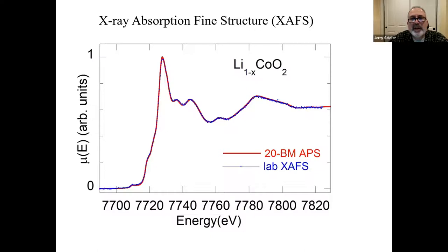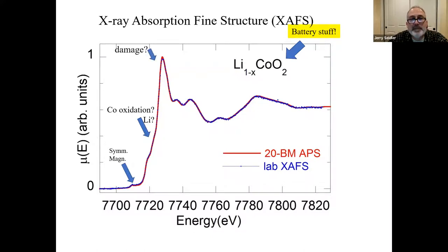Of course, there's a considerable infrastructure for interpreting these spectra, but extremely briefly, and it's a battery material. From the pre-edge features, you can often learn about symmetry and sometimes about magnetism of a material. From the position of the edge, you could learn about oxidation state, in this case, possibly lithium content. That peak in some papers seems to correlate with damage in the battery material.